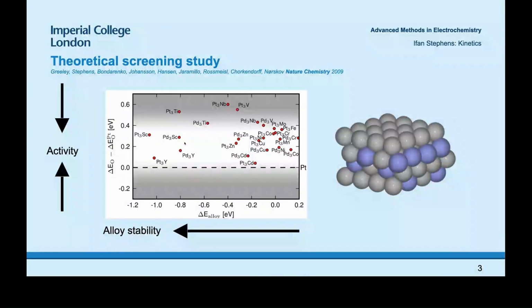And anyway, then I started trying to make sure that the benchmark platinum I used agreed with the literature, and I found out, to my disappointment, that the platinum activity was actually lower. So the platinum activity that I'd already measured was lower than the state of the art in the literature. My own platinum experiments were really inactive, and palladium yttrium only performed better than the really inactive version of platinum that I'd done. So basically, I'd done all the experiments wrong on the benchmark platinum.